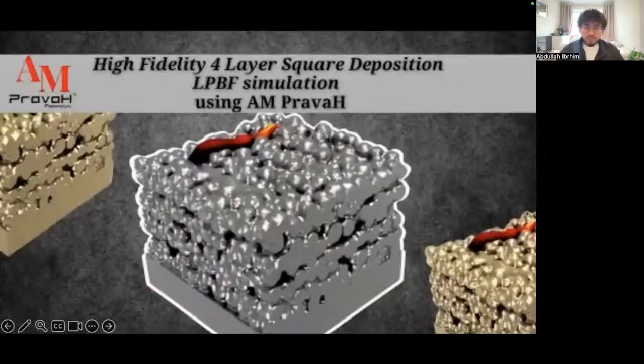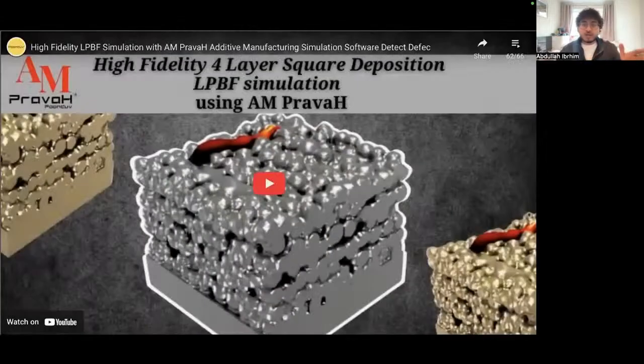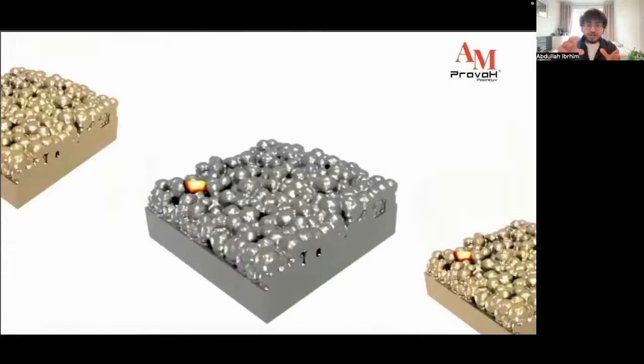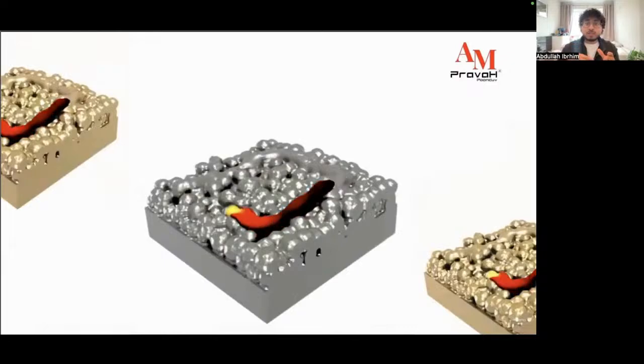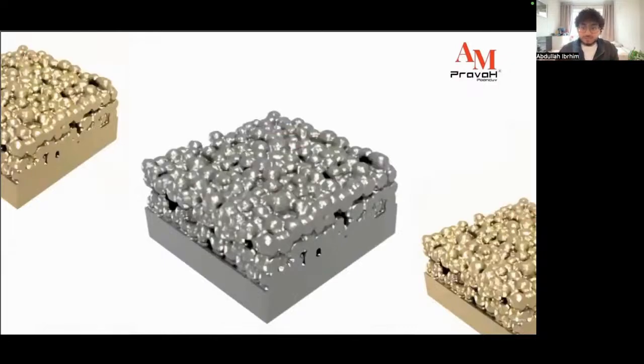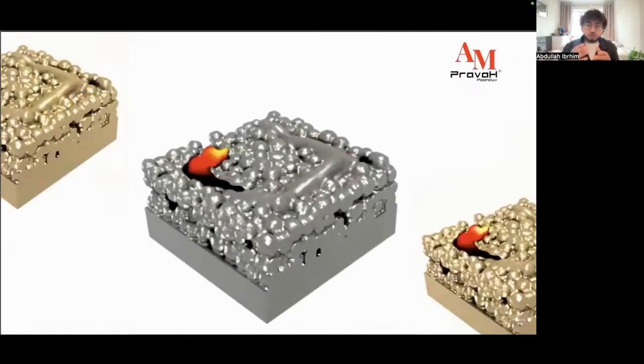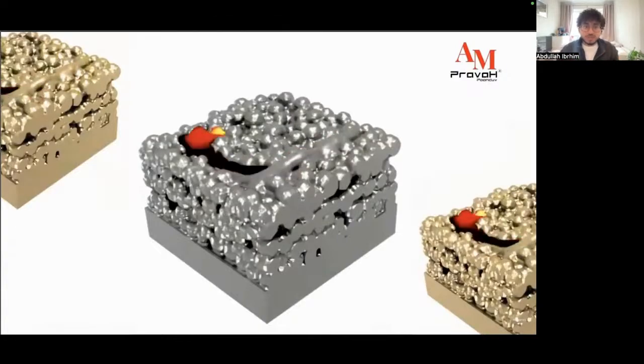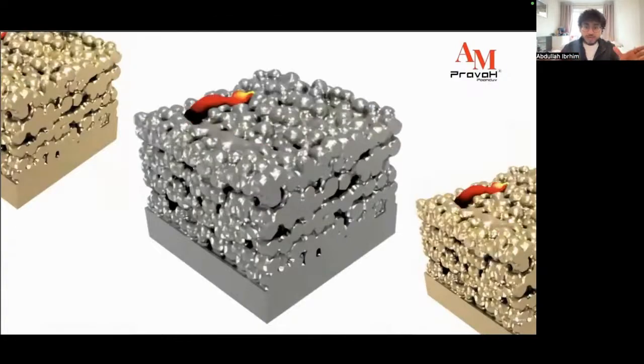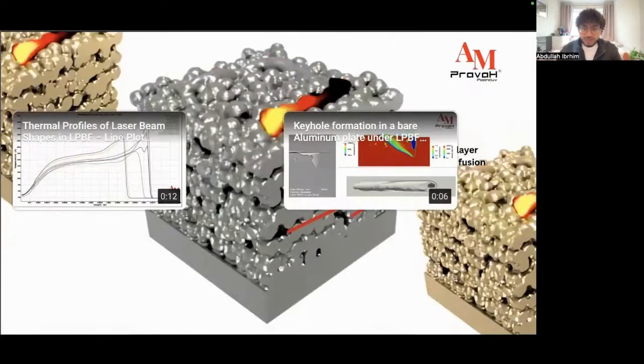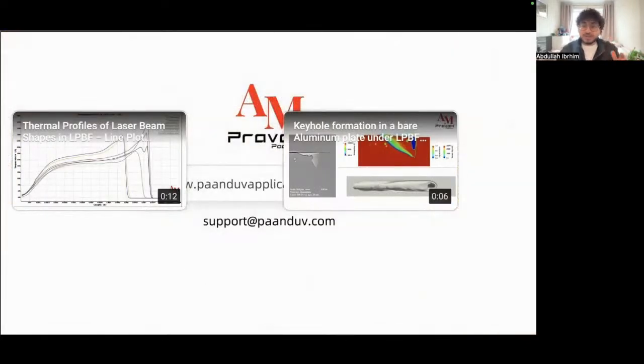So in this video, you can see a higher fidelity 4-layer simulation. Fewer layers, but this video really showcases the fidelity and depth of AM PravaH's physics-based simulations. You'll notice that within the simulation, the software captures an interlayer lack of fusion, and the simulation identifies these defects caused by low laser power or high scan speeds, could be either, and then offers crucial insights into process optimization. Now, after the third layer, you'll also notice stable patterns. By the third layer, stable deposition patterns are observed, indicating consistent layer buildup and enhanced process stability.